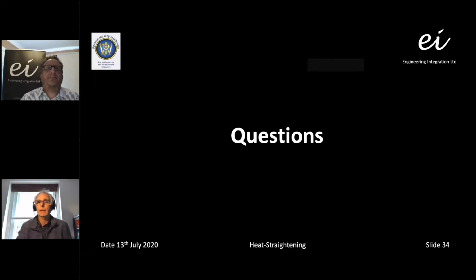Okay, thank you. Right, we've got a question from Andrew Wilson, and he's asking, is 650 the top temperature you use? It is the top temperature that we would use, because if we go beyond 650 degrees C, we start changing the crystalline structure. Anybody who's into their metallurgy knows the carbon starts to come out of the crystalline structure at 650 degrees C, and if it's not allowed to cool very slowly, you can actually get carbon embrittlement within the steel, and therefore that obviously is not something we want, because the steel becomes more brittle and we can get brittle fractures occurring and what have you. So we do limit it to 650 degrees C because that is considered to be our critical temperature.